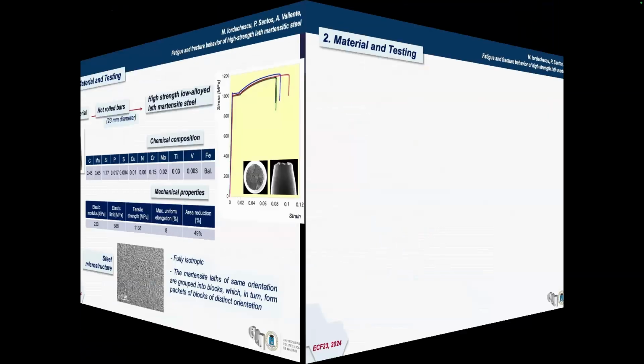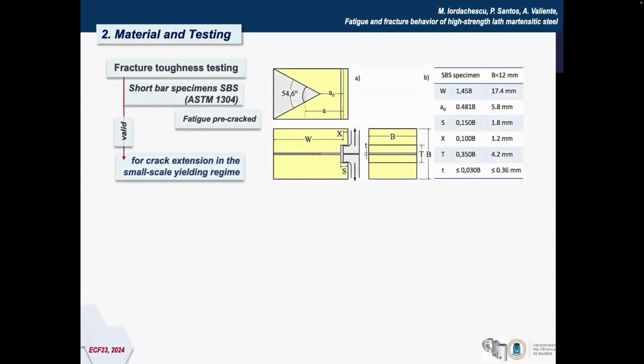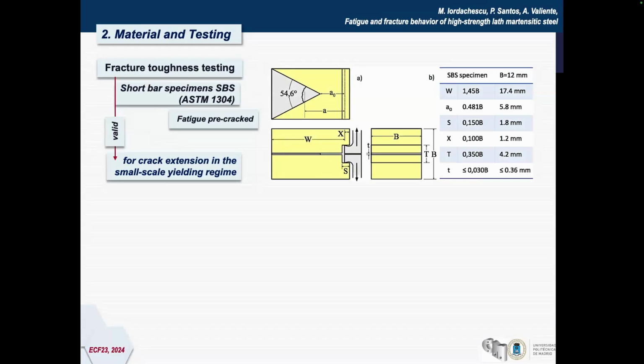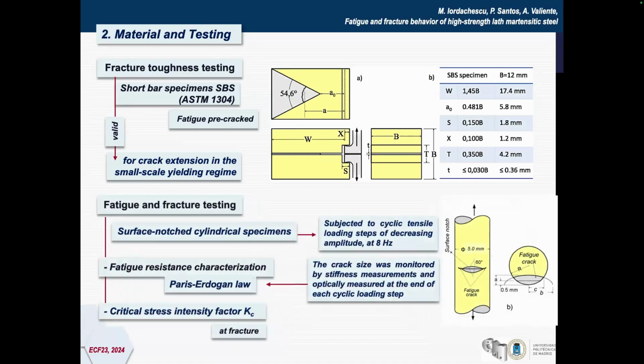isotropic. Now, passing to the testing, for fracture toughness, we used short bar specimens as per ASTM E1304, but we modified something to be sure that the crack extension is in the small scale yielding regime. Practically, we used pre-cracking from this chevron notch. For fracture and fatigue testing, we used the surface notch cylindrical specimens as presented here.